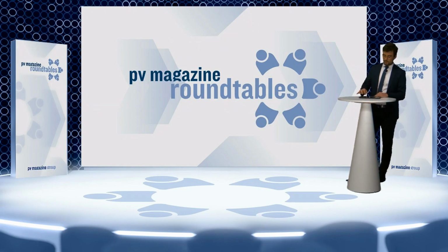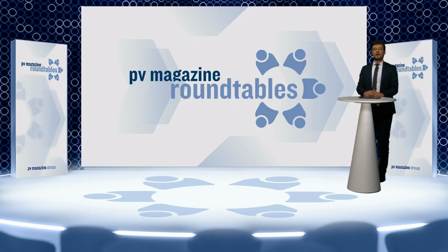Well, one way to address this issue is by taking out the element that's actually causing it, because it's caused by the boron-oxygen complex. Taking out the boron and replacing it with gallium is promising and has resurfaced as a solution after a cross-licensing agreement was made by LONGi with Shin-Etsu. My next guest, Monsoon Wang, is the product director of module manufacturer LONGi.